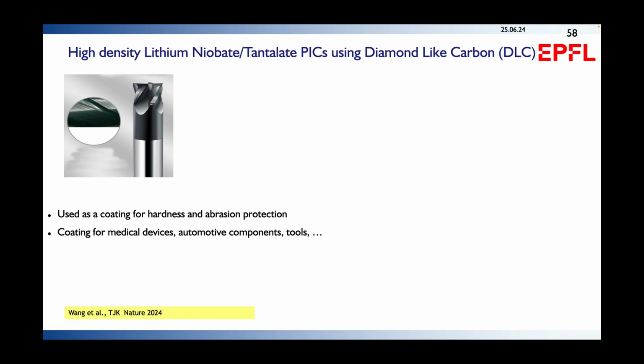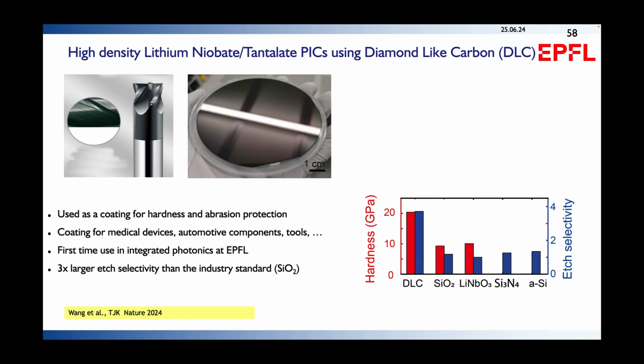And so what we've discovered and what we've used in my lab is a material that many of you may have used this morning inadvertently. For instance, if you shave in the morning, your razor blades have a material on top of them called DLC, diamond-like carbon. Diamond-like carbon is a material that can be generated by methane decomposition, so very easily in a reactor. It coats conformally. It has the hardness of diamond, with strong sp3 hybridizations in carbon, and can be used as a coating for medical devices, tools, automotive components.